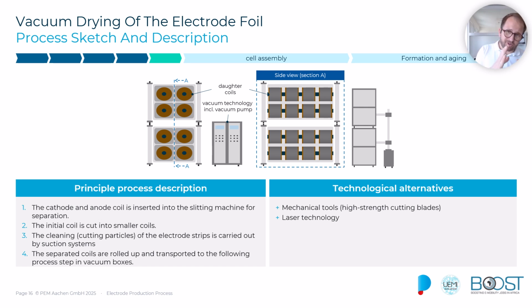So before transferring the coils now into this dry room, there's normally this vacuum drying process and making sure to really bake out the last bit of water. So the foils are basically pushed on a special goods carrier into those vacuum ovens, and then they are stored there in a controlled environment for many hours, 12 to 30 hours, before then transported really into the production of the battery assembly process. So any residual moisture or solvent can be reduced out of the coils.